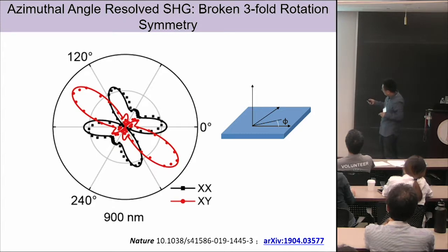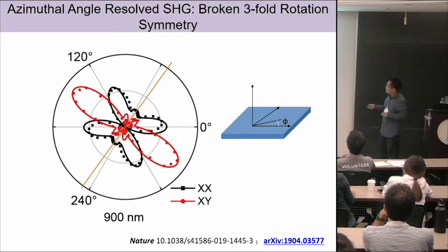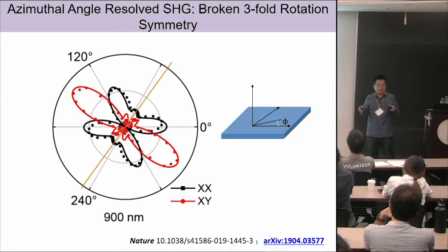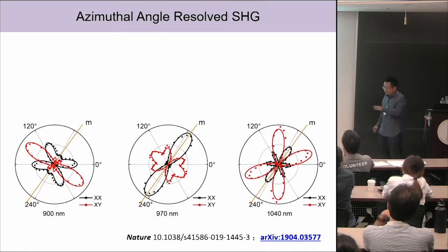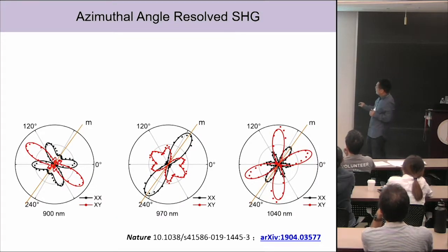But if you look at it, you clearly see there's a mirror plane here, right? And the solid line I show here is the fit of the data using the C2h symmetry, all right? So basically, the bilayer actually looks like a monoclinic structure. To confirm that, we can also do the same measurements, but using different excitation laser energies.